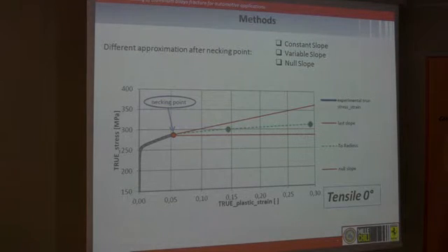In our case, we use only 2 points beyond the necking, or equivalently 2 values for the post-necking slope, in order to simplify this phase. Using 2 points only, we expect a rough approximation of the post-necking force displacement curve. However, a more precise result would also require more specimens due to unavoidable experimental scattering.